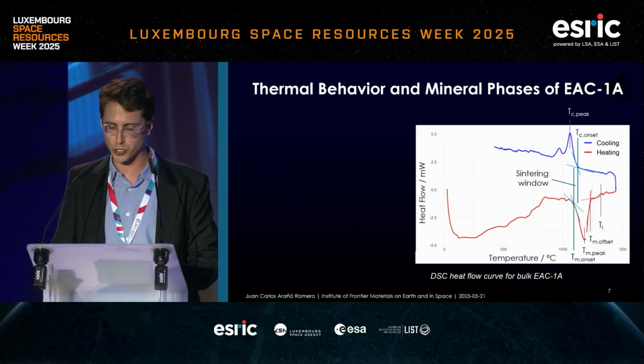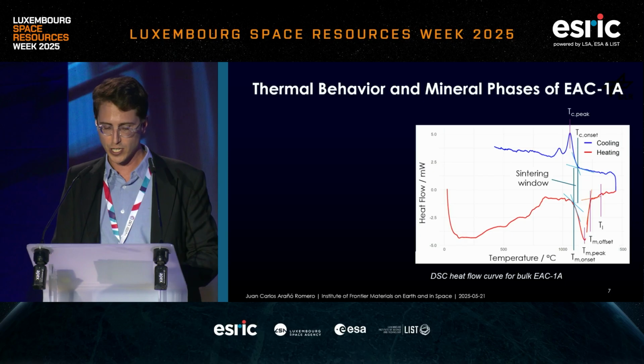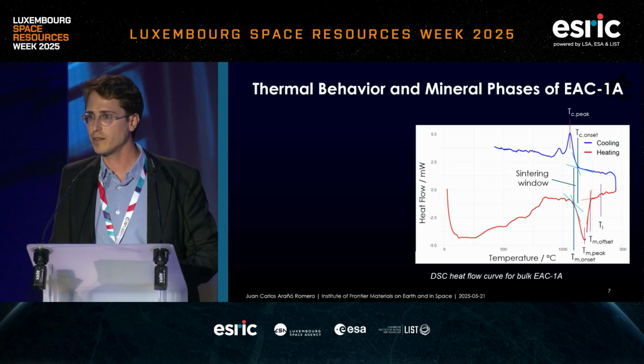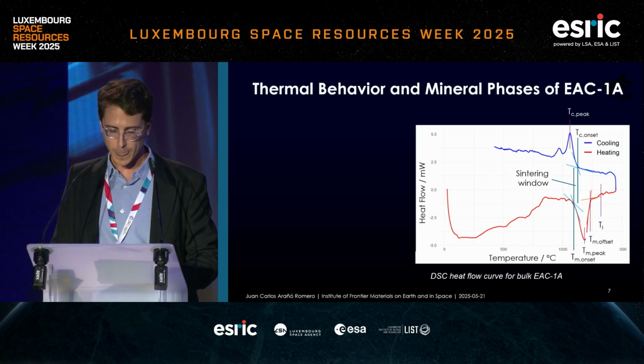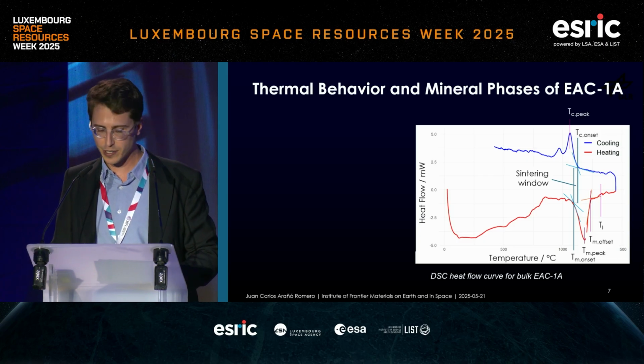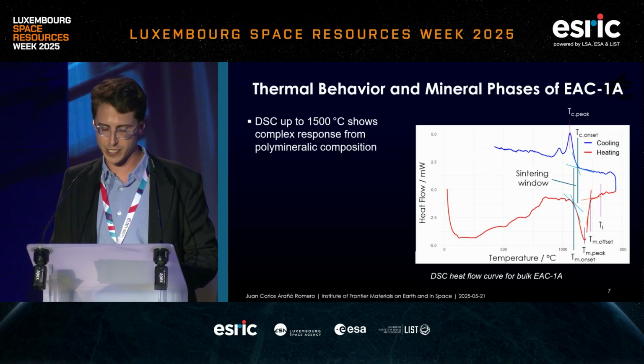So to understand the sintering behavior, we ran a differential scanning calorimetry up to 1,500 degrees Celsius, and this curve shows a complex thermal response. And this is due to the EAC1A being a mixture of many minerals. So you can see also a wide sintering window, meaning there is flexibility in processing temperature.